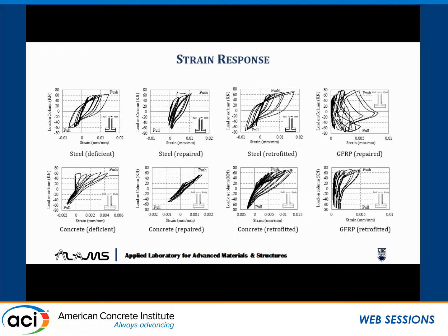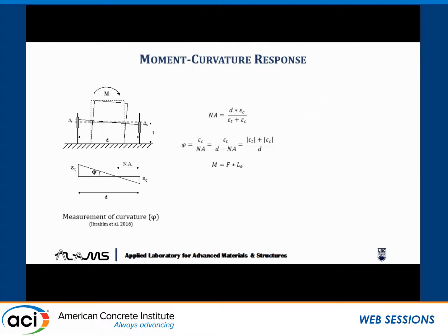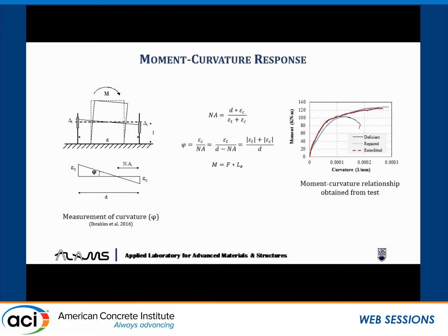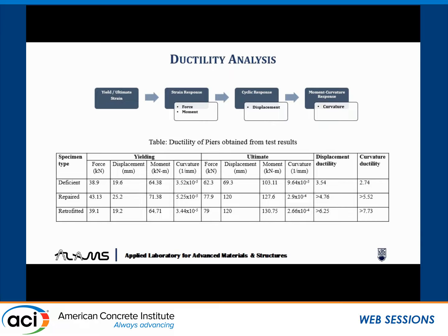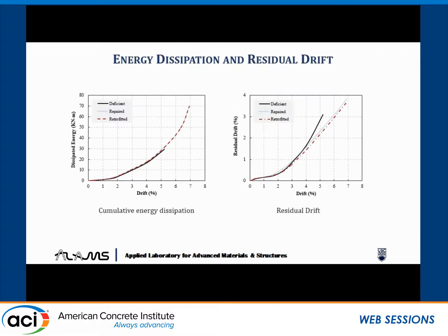We also observed the strain response of all those columns, and we also observed the moment curvature response, and we found that the curvature ductility and displacement ductility all increased significantly compared to the deficient pier. And we also observed the energy dissipation capacity. So obviously they went to larger drift and they could dissipate much larger energy. And we also observed the residual drift of the repaired and retrofitted specimens. In both cases, you see that they are almost identical.